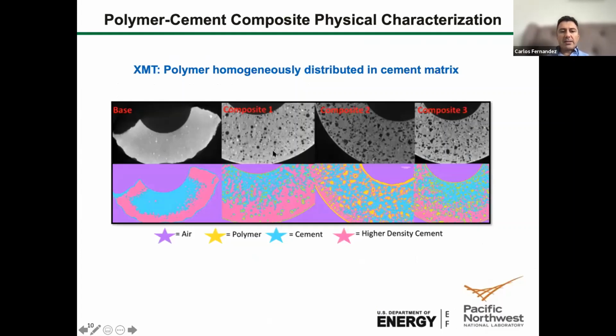This is a control cement, and these are X-ray microtomography images, and you can see here 3 different composites and how the polymer, in yellow, is homogeneously distributed and even migrates to the interface of the cement casing. This was confined cement with 2 concentric casings, one in the center and another one surrounding. And you can also see that in all cases, the polymer not only is homogeneously distributed in the cement matrix, but also migrates to the surface. And that's also important because if we have interactions with the casing or the formation, you can increase the adhesive strength and the recovery of adhesive strength per shear stress.